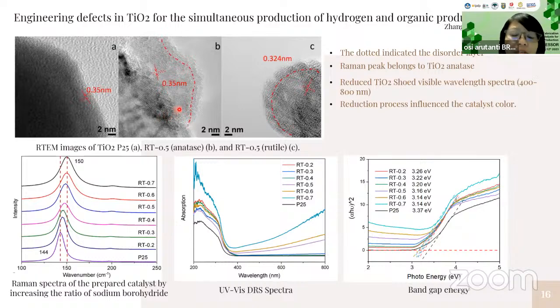If in the previous paper they used hydrogen gas as the reduction agent, here they use only sodium borohydride. The TEM image shows that after the reduction process, they get a disordered lattice fringe, which is due to the defect crystal. And how about the Raman analysis?